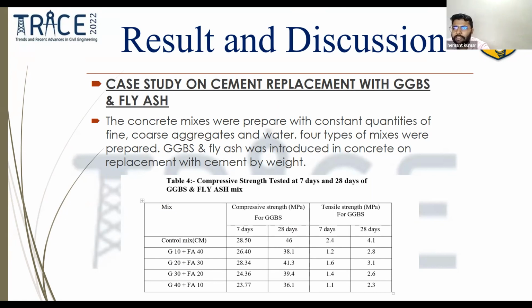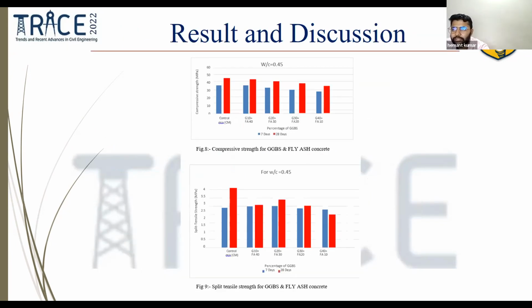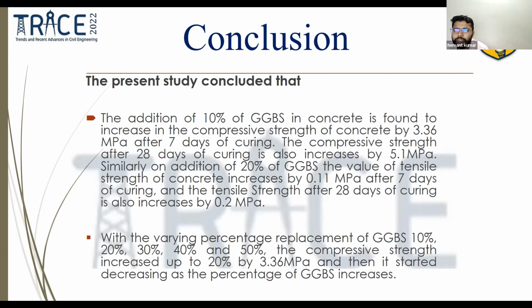So we get these results. These are the charts. So our conclusion is the addition of 10% of GGBS in concrete is found to increase the compressive strength of concrete by 3.36 megapascal after 7 days of curing. The compressive strength after 28 days of curing is also increased by 5.1 megapascal. Similarly, on addition of 20% of GGBS, the tensile strength of concrete increased by 0.11 megapascal after 7 days of curing, and the tensile strength after 28 days of curing was also increased by 0.2 megapascal.